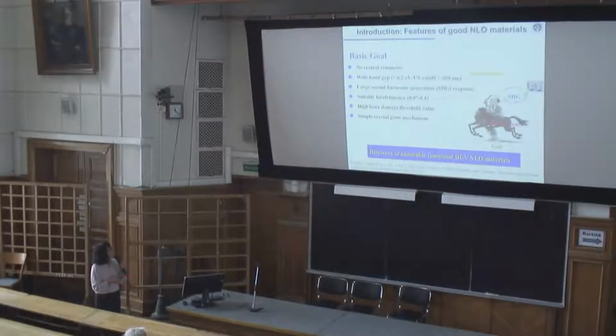But usually these two properties are in contradiction, so we should make a balance between them. Another thing is that the birefringence should be suitable, meaning not large and not small, so there is a region. For this suitable birefringence, usually it may bring some layer tendency. In that case, the crystal cannot be grown as a large crystal. It's just like you want a horse to run very fast, but you don't want it to eat, and you also want this horse to be very handsome. Usually it's very hard to satisfy all of these in one material.